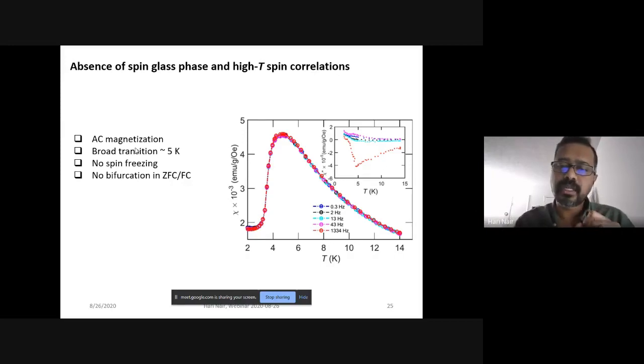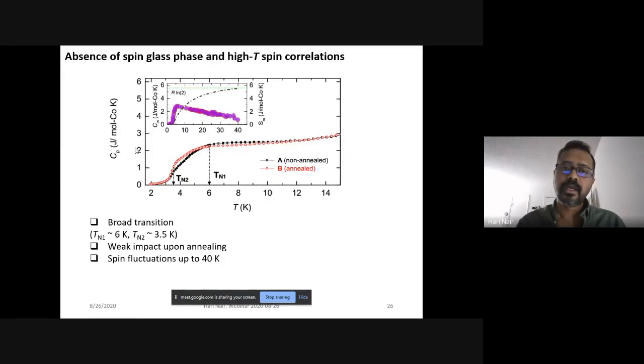So in this particular case, even though we varied the frequency over a couple of decades, there was no such frequency dependence. All the curves fall on top of each other. If you measure specific heat, you would see a clearer indication of the two anomalies at around 5 or 6 Kelvin and around 4 Kelvin, which is more clear in specific heat.